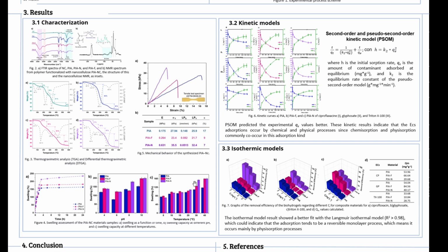The figure displays distinct peaks associated with carbons in the biohydrogel molecule. The peaks at 173 and 171 correspond to the carbonyl groups of itaconic acid. The peaks between 50 and 100 belong to the nanocellulose structure. These are weak signals due to their low concentration in the biohydrogel. Also, the figure shows an inset with the proposed structure of the biohydrogel, where mainly the backbone formation was in the double bond carbon of polyitaconic acid. This confirms that the interaction between nanocellulose and polyitaconic acid was by hydrogen bonds.